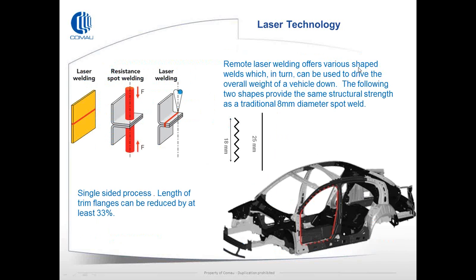Remote laser welding offers various shapes in terms of the welds, which can drive the overall weight of the vehicle down. The following two shapes show, in terms of an 8mm diameter, a typical spot weld. So with a perforated 18mm or a straight 25mm remote laser weld joint, it's given the typical performance of an 8mm diameter spot weld. But what it does do, if you look on the left, it can give dramatic savings in terms of weight. So the flange width required for a resistance spot weld compared to what's required for a laser spot weld is dramatically reduced. So potentially you can reduce the flange length by up to 33%.